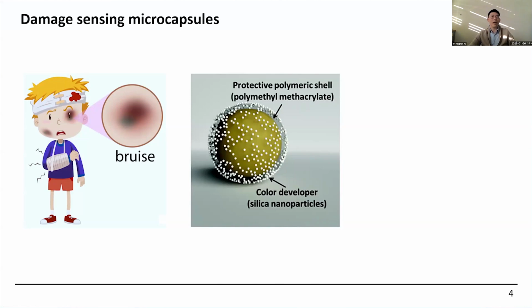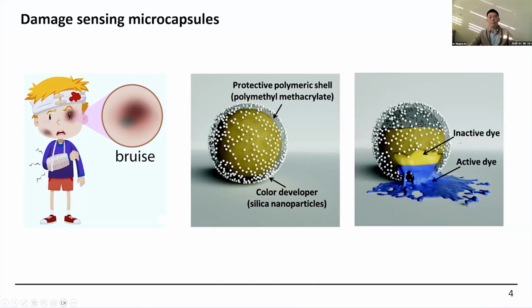We can use the microcapsule to realize this. The strategy is that the microcapsule has a core-shell structure, and inside we have a liquid core filled with dye, which can be either a normal optical dye or a fluorescent dye. Once the microcapsule is broken by external force, for example cutting or bending, it releases the dye inside, and this dye can be active to show the optical signal.